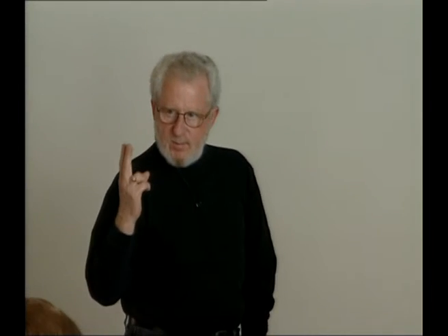This picture is highly idealized. Two things in particular. I've left out disorder in this simple picture. We know that these systems are not single crystals, so we know that disorder is important. Turns out that if you take a sample of the kind that I passed around and put it in front of an X-ray beam and look at the diffraction, you will see some crystallinity. So this material is not completely amorphous. Some of the polymers that we deal with are basically completely amorphous. But as a result of the disorder, this picture is idealized.